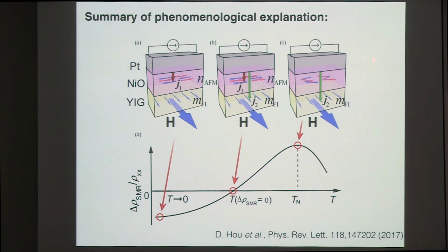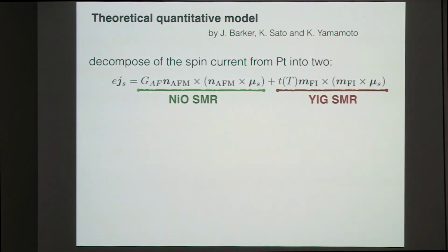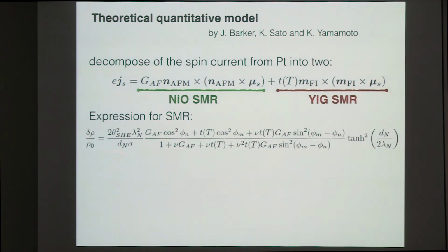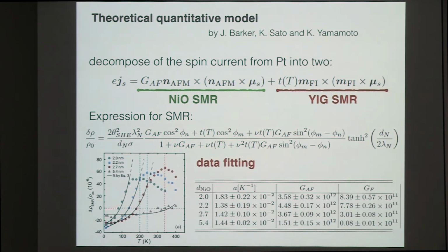And above the Néel temperature, or around the Néel temperature, you just have the normal SMR due to YIG. There is no antiferromagnet nickel oxide anymore. So actually, we try to be a little bit quantitative because we have the theoretical curves, which are also here. We can make this equation pretty complicated to fit the data just below the Néel temperature, and get the effective numbers of this mixing conductance. So actually, we look at it, we will find that the nickel oxide platinum interface is not so bad.